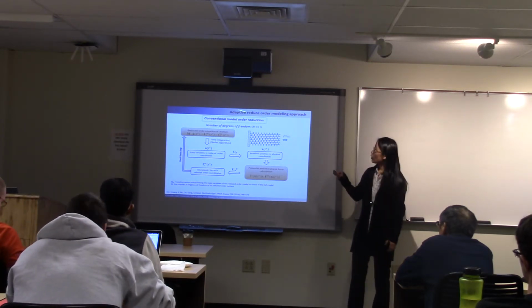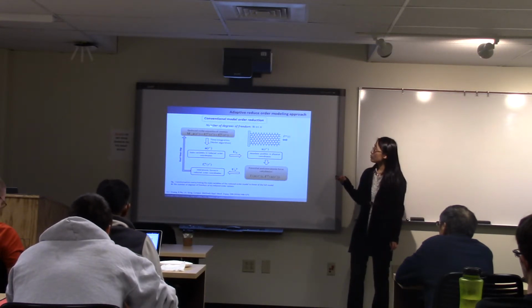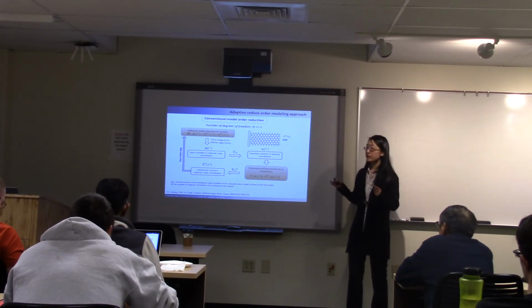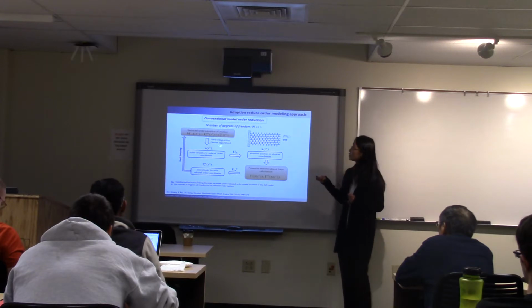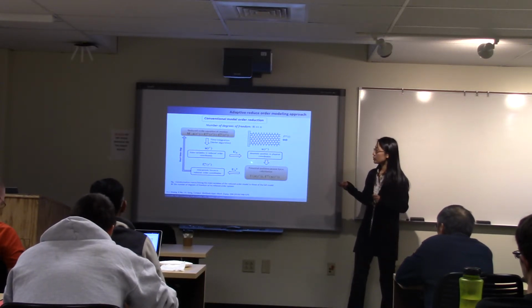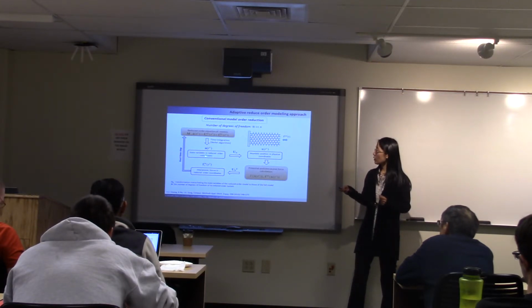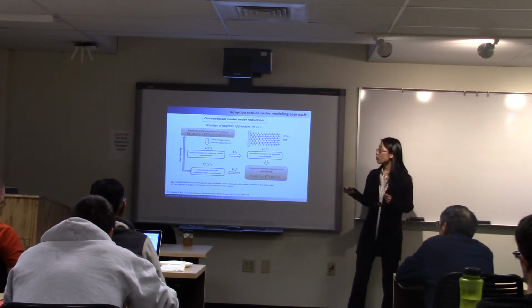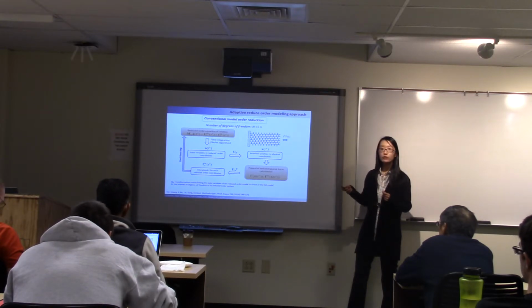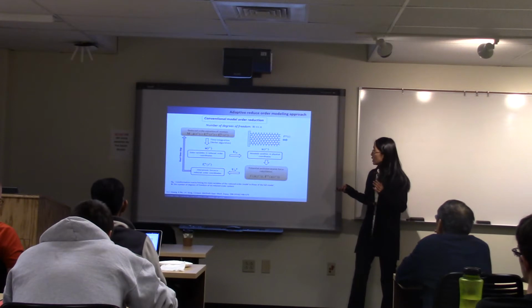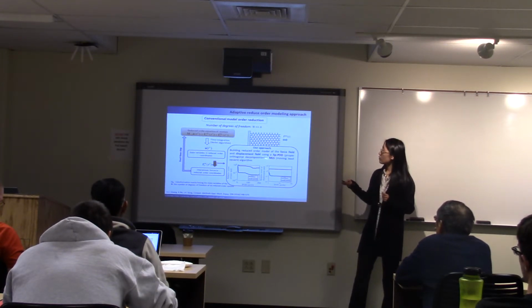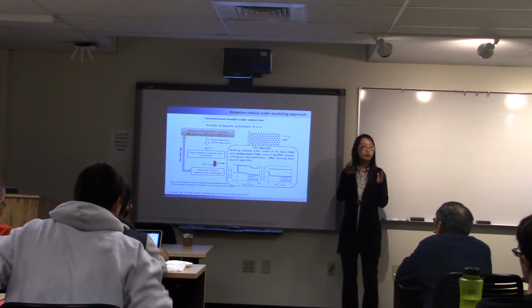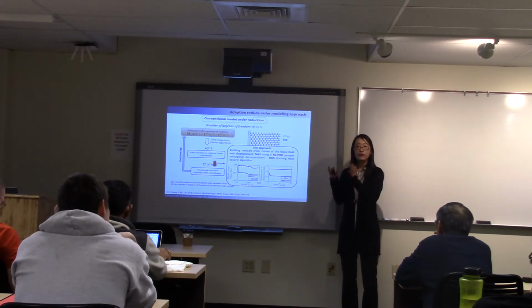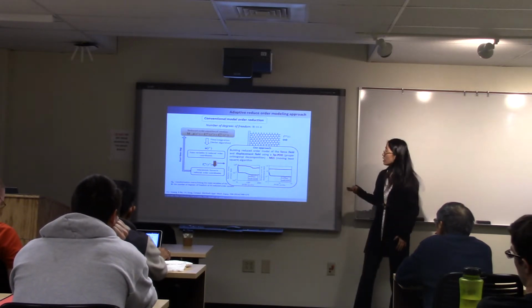So in this case, model order reduction is a good option because it can greatly bring down the number of degrees of freedom of the original full atomistic system. But the problem in conventional model order reduction is that we need to do the online projection between the reduced order coordinates and the physical coordinates very frequently, which is very computationally costly, because we only build the reduced order model for the displacement field. So in our approach, we build a reduced order model of the phase field besides the displacement field using HPPOD, proper orthogonal decomposition, and the moving least squares algorithm. That will save the time to project between the reduced order space and the physical space at the online stage, which further saves computational cost.